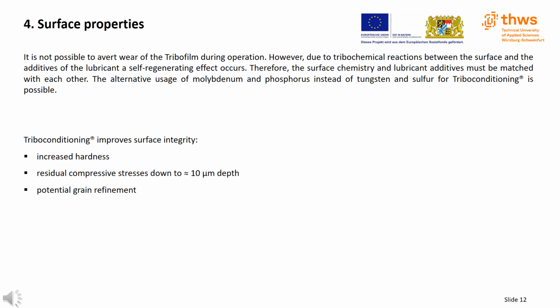An alternative for tungsten is molybdenum. Furthermore, sulfur can be substituted by phosphorus. In addition to friction and wear behavior, triboconditioning also improves surface integrity. The near-surface compaction leads to increased hardness and residual compressive stresses down to a depth of approximately 10 microns. In addition, grain refinement can potentially occur due to deformation and friction during triboconditioning. This would have a positive influence on strength, toughness, hardness, as well as tribological properties.